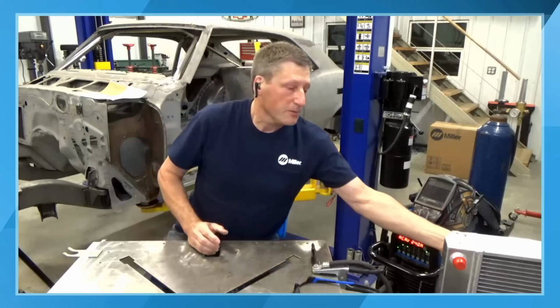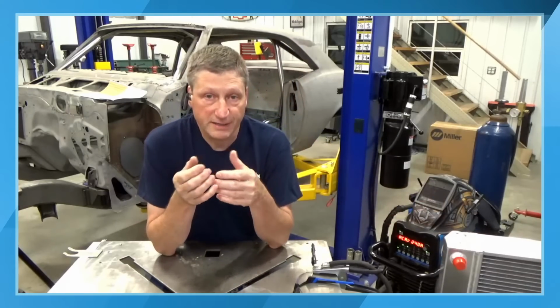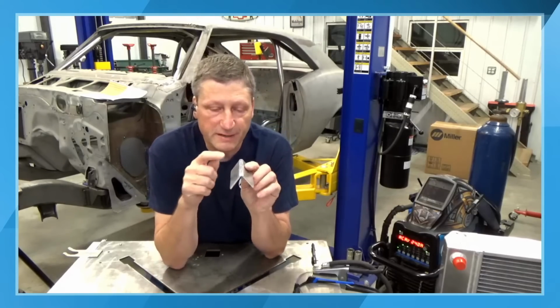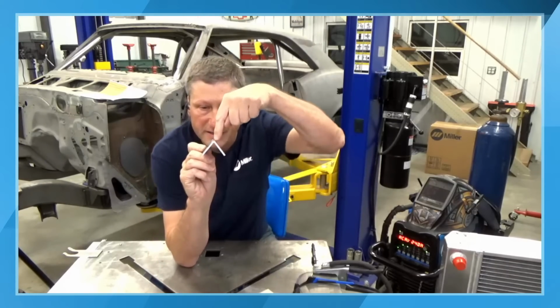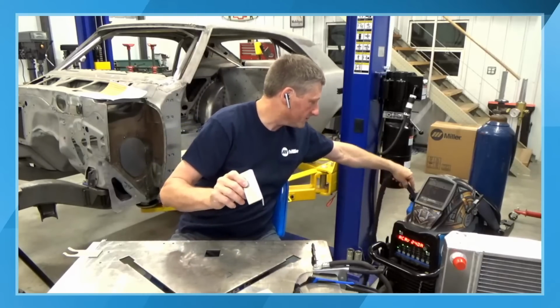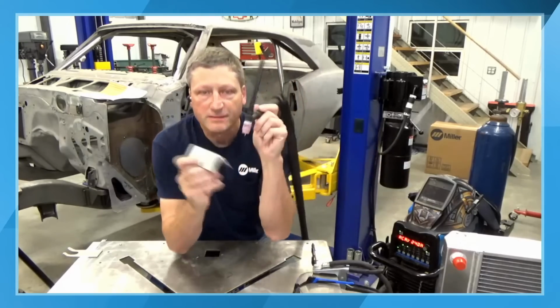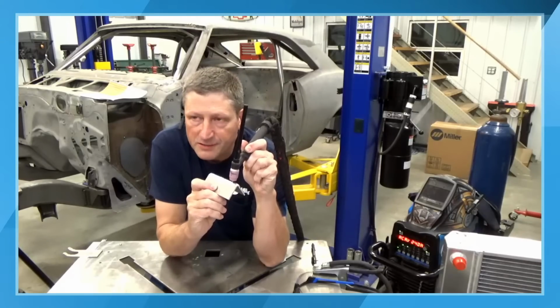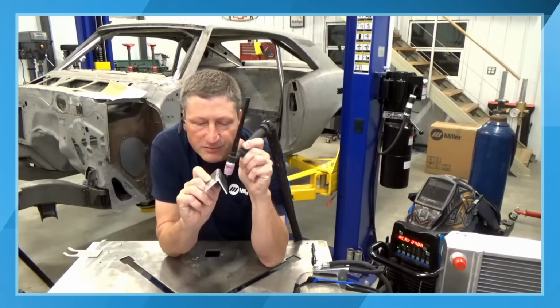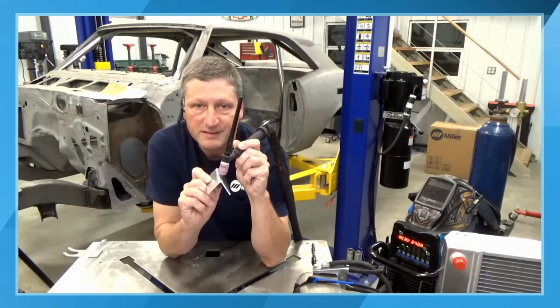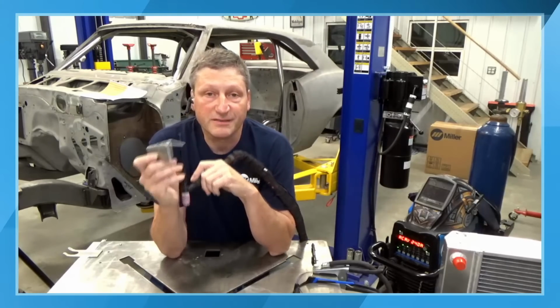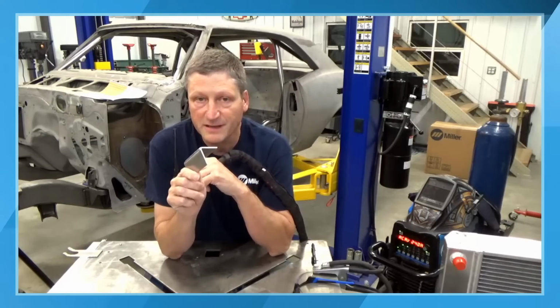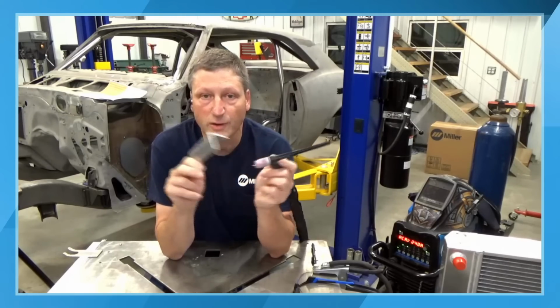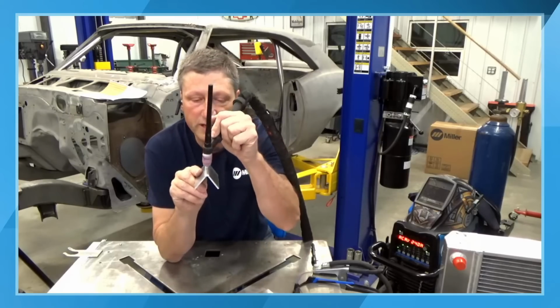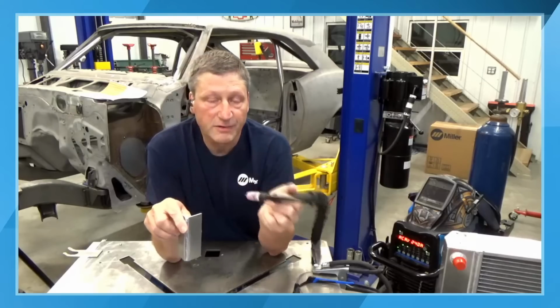Okay. Now, you can change that by joint design. And the reason I adjust my balance is because if the metal is falling away from your tungsten, okay, so you're welding this in this configuration. Now, the base metal is falling away from the tungsten, which means the AC isn't going to be as effective on cleaning this piece because the base metal is farther away from the tungsten. So I need to lower my balance when I'm doing an outside corner. Now, inversely, that's not true.